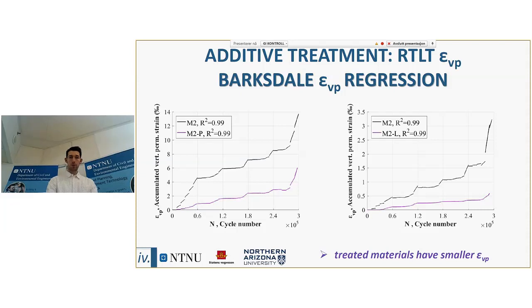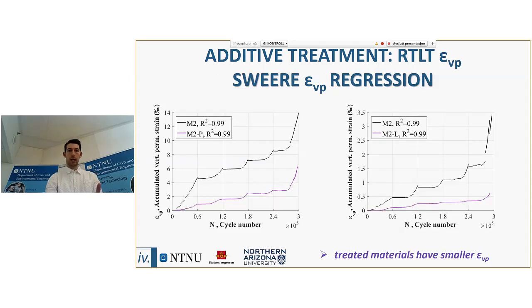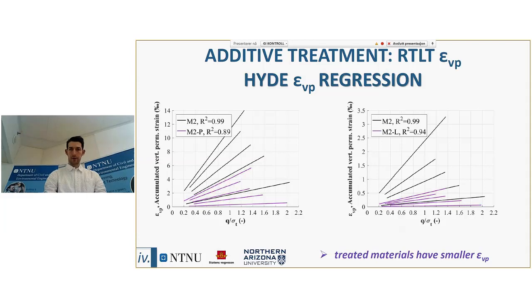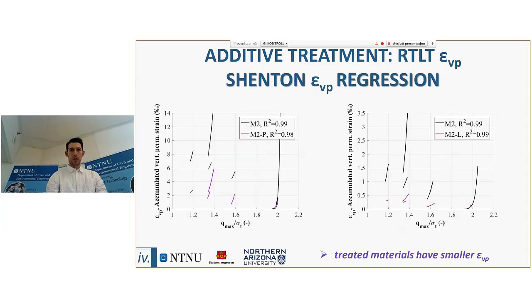So the first model we considered was, of course, the Barksdale model. It's very clear that the accumulated vertical permanent strain, the magenta ones here, is much lower than for the untreated materials. We had very similar results with the Sweere regression model. Again, if we consider the Hyde regression model or the Shenton model, the magenta data, that is to say the permanent deformation connected to the treated materials, was always much better than the permanent deformation properties connected to the untreated materials.